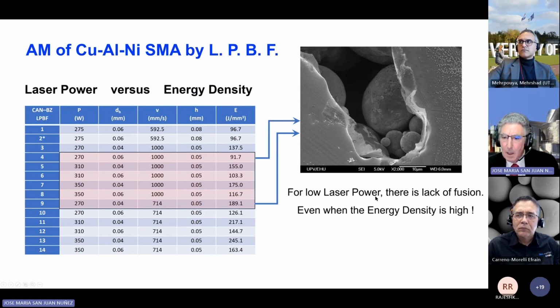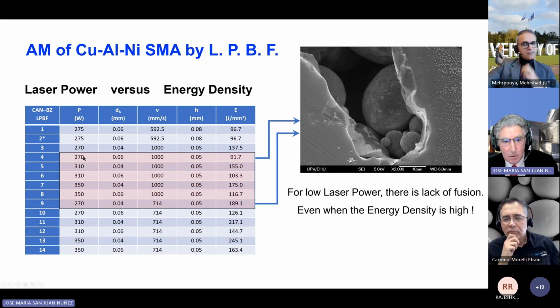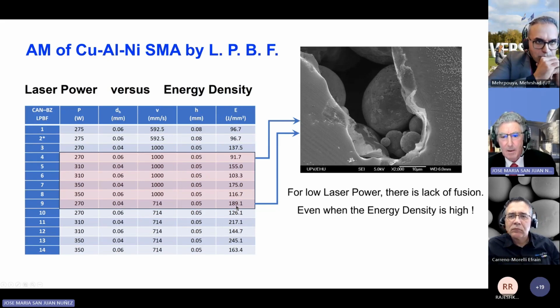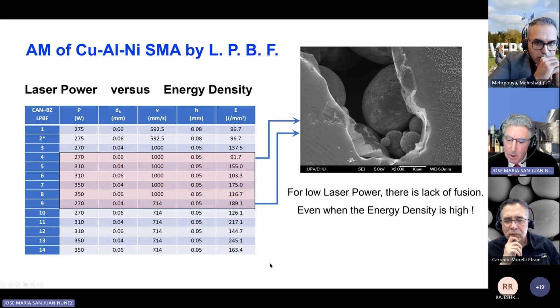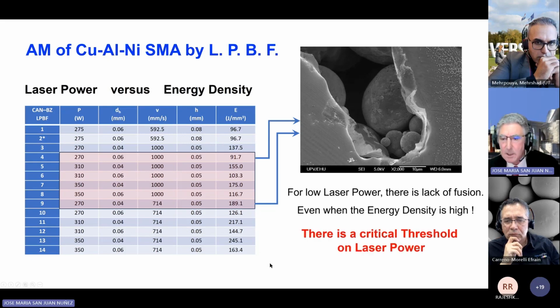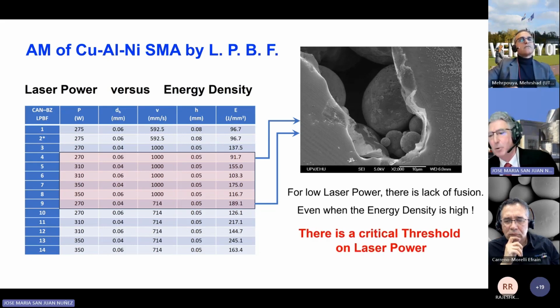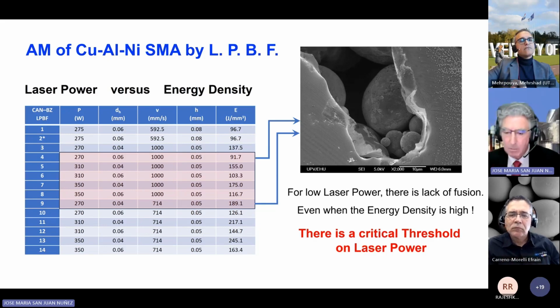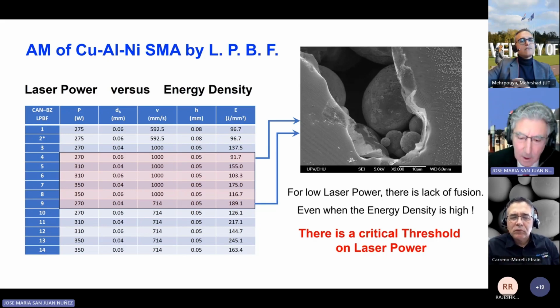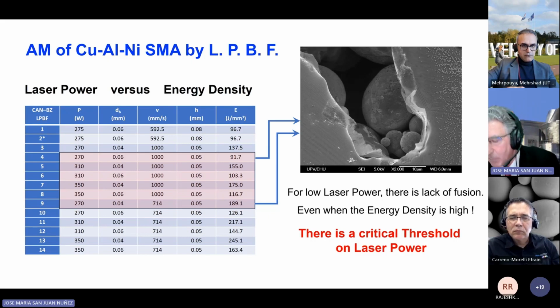your material. And the point is, even when the density of energy is high, because you can see here, with the same power, but because of different parameters, we can get here a much higher energy density than in this case, and in both cases, we obtain this problem. So this is an important point because it means that there is a critical threshold on laser power. If you have not enough power, you cannot guarantee the local melting of the alloy because of the high thermal conductivity of the copper-based alloy.